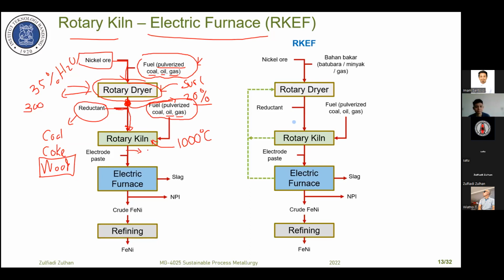The product is the calcine, at a temperature roughly between 600 and 800. We transfer this calcine to the electric furnace, charging it at maybe less than 600, because there is some heat loss during transportation and when we put it into the bin. The temperature of calcine charged into the electric furnace is around 500 to 600.